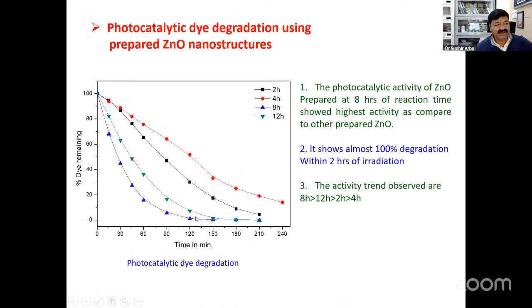So this is what we did. We converted this percent dye remaining versus time, and we observed that this material is prepared, zinc oxide is prepared, and we studied its catalytic degradation. So here what we observed, this material prepared at 8 hours is having highest degradation. Using this chemical kinetics, we can identify which material is best. So here the activity trend observed is 8 hours is the best, then 12 hour, 2 hour, and 4 hour.